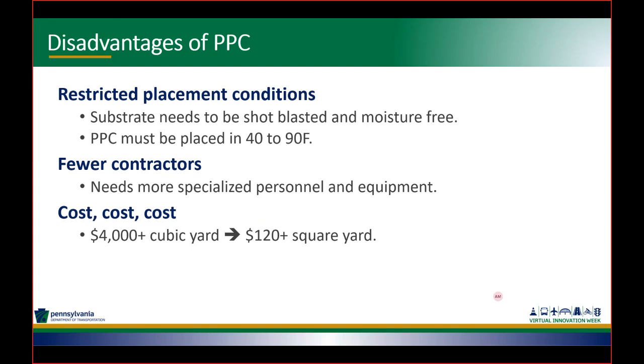A little bit of the negatives or disadvantages of using PPC. There is prep work like you would do for an epoxy overlay, and you need to have a moisture-free deck. So there are years that are challenging to find windows of opportunity to place the material, because of the moisture mainly. Also, the temperature range where you can use PPC is 40 to 90 Fahrenheit. So during the summer, you may have to do a night placement because you don't want to place it at a temperature above 90 degrees.